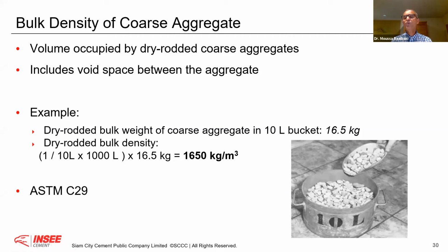Therefore, this is a good indication that is integrating the physical aspects of the coarse aggregate. That is very interesting. Sometimes you can go down to 1,550, you can go up to 1,700, 1,800. With a favorable coarse aggregate, you increase this value, considering the same parent rock. You have a standard for that, which is ASTM C29.